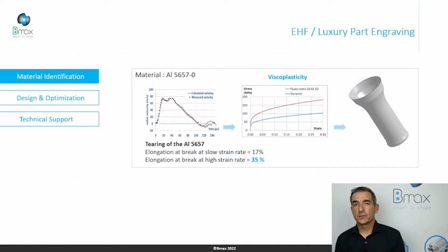The first step consists of performing the material characterization in static and dynamics. The aluminum 5657 annealed has been chosen by the customer to get the brightness after anodization. We define the material curve, the strain hardening curve in static and dynamics, and we track when the necking occurs to define an elongation at break with high strain rate. It's 35% in this case. And we use all this data for the sample on the right.